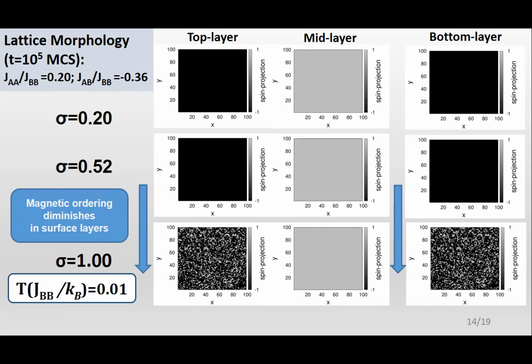is basically a manifestation of what the external field has done to the system. We see that where the in-plane coupling strengths are weaker, that is in the surface layers, the magnetizations are mostly affected, and in the mid layer, where the ferromagnetic in-plane coupling is the dominant one, there the magnetic ordering remains almost unaffected.